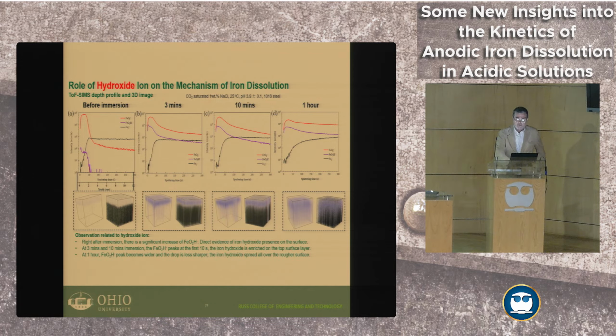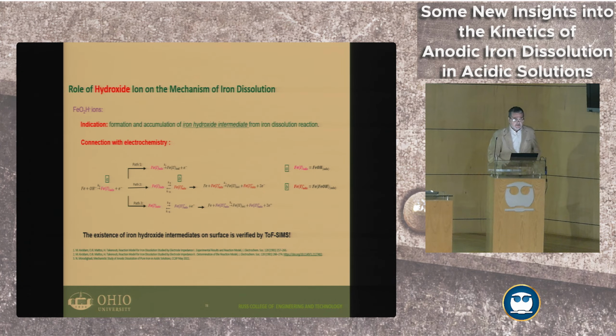So if this iron is going to dissolve into the solution, it first has to become hydroxide and then it has to go into the solution. It can't jump out, it just cannot send electrons out and go out in the solution. It does have an intermediate species, in this case hydroxide. So Heusler in 1954 was right. And so was Bockris in 64, and everybody else that followed. Not a new story, but here is a direct proof. Yes, these hydroxides are an integral part of a corroding surface. So they were right.